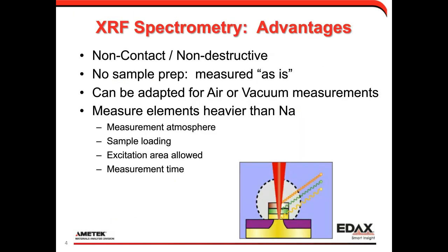Okay, the biggest advantage in using XRF spectrometry for analysis is that it's non-contact and non-destructive. We can also measure the samples as is. We don't have to do any sample prep on them, which makes it ideal for process control, because you don't really want to do a lot of sample prep in that kind of environment. The technique can be adapted either to an air atmosphere or a vacuum atmosphere. And in general, we measure elements heavier than sodium.